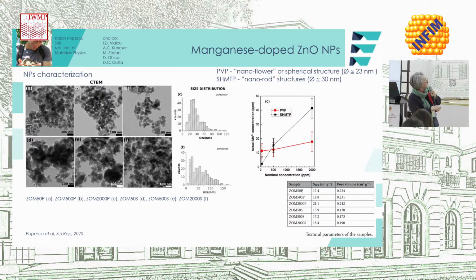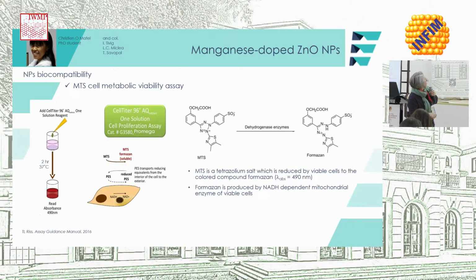And the nanoparticles were fully characterized by our colleagues from here. So we knew the dimension, the size distribution, the actual concentration of manganese, some textural properties of the samples, all these parameters. And then Christian performed the classical MTS, which you know is the procedure to evaluate as an endpoint test the viability of a cell, in fact, of the mitochondrial enzymes' capability to produce that colored formazan.